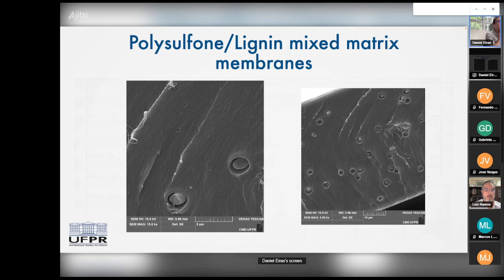around the particle. So what we believe happened here is that although we had the nanoparticles incorporated in the polymer, those nanoparticles were not compatible with the polymer. There was a problem of interaction. So what happens here is that the gas, instead of passing through the polymer or through the particle, is going to come around and simply pass around the particle. That explains why we don't have selectivity in many of our membranes.